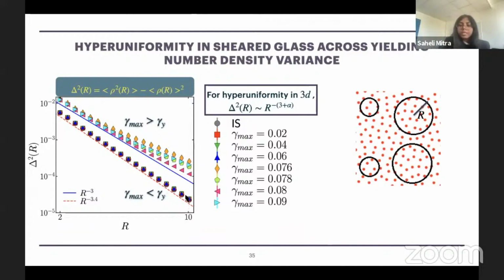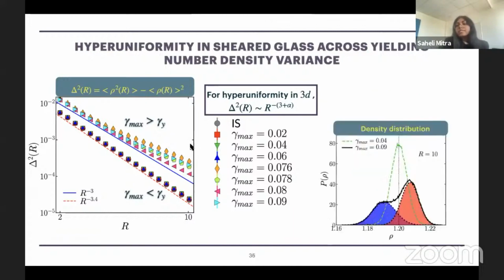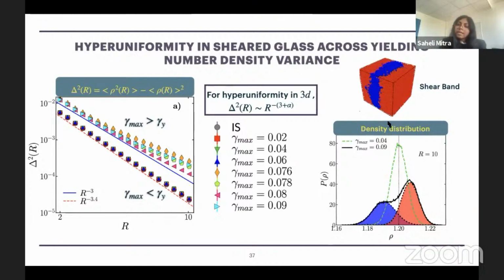For that, we choose one particular window size, r equal to 10, and we see the probability distribution of the density field below and above yielding. We find that below yielding, the probability distribution of the density has a single peak around the bulk density 1.2, whereas above yielding, it has two peaks, one at a density lower than 1.2 and the other at a density higher than 1.2. From the extent of the distribution above yielding, we can see why it will have strong fluctuation. So we now want to see where these two distributions are located in our simulated system. We see that in fact these two distributions are localized in space, and that actually coincides with the shear band present in the system.